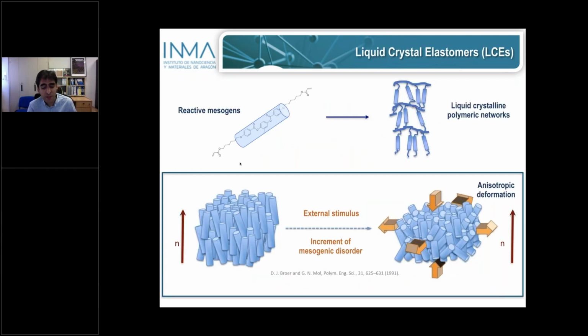And in this field of soft actuators, we focus on this family of materials, liquid crystalline polymeric networks, that are composed by these elongated rod-like molecules that are incorporated into the polymeric network, as shown in the cartoon in the upper right part of the slide. Importantly, these materials present an anisotropic deformation when they are exposed to an external stimulus, for example, an increase in temperature.